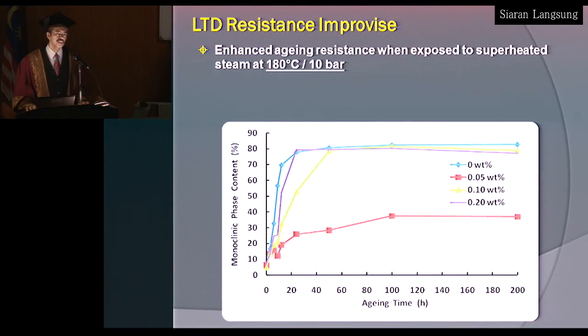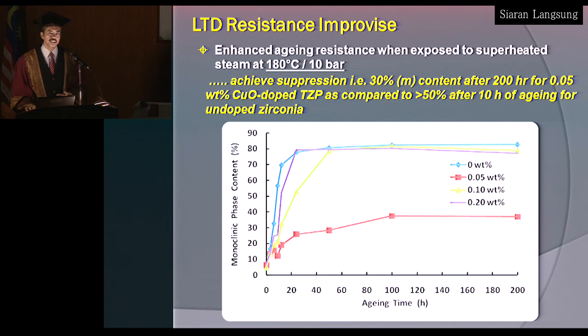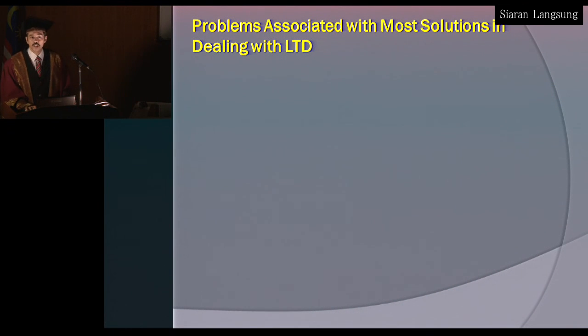In terms of LTD, low temperature degradation, there is some improvement. As the graph shows, with the copper oxide doping, we managed to suppress the phase transformation, but not to prevent it. It still happened, but the amount of transformation is lessened. So we obtained with 0.05% copper oxide doping, the monoclinic phase is about 30% as compared to the undoped. So is that good enough? That's really not good enough.